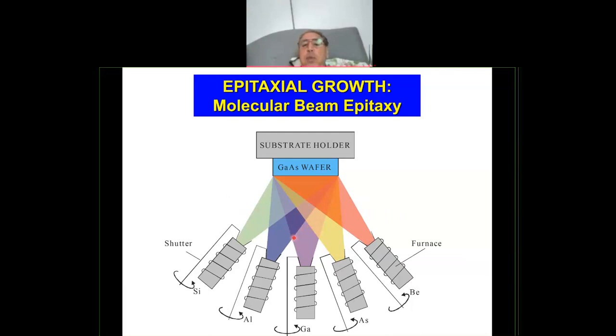The way you form this solid structure is that you load furnaces with aluminum, gallium, and arsenic. In front of each furnace you have a mechanical shutter, so you can open and close it. They are very fast acting shutters. These allow you to build the semiconductors, but pure semiconductors are not very useful, so you need some dopant. You have to make them N-type and P-type, as most devices are based on a P-N junction. In MBE, we use silicon atoms to make electrons, to make them N-type, and we use beryllium to make them P-type. So we can grow any structures we wish, and dope them N-type and P-type.